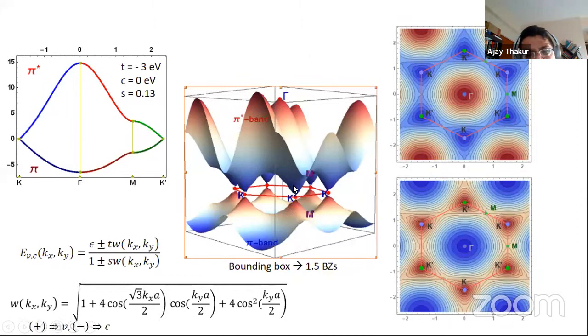And if one zooms in on this, one gets a dispersion, a kind of double cone-like structure. So in the vicinity of this point, there is a cone-like structure, which is called the Dirac cone. And these are the 6 equivalent points about which the system has a metallic character. Then the M points are the ones where you can see there is a natural gap. So if we look at these M points, when we go from the pi band to the pi star band, there is a finite gap, and this is insulating.